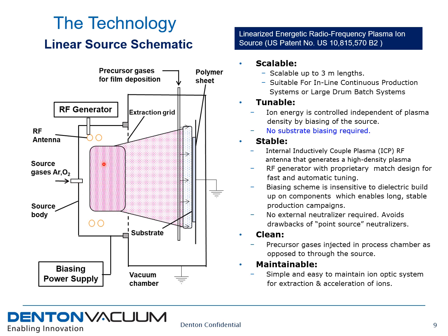and the ions are accelerated to the substrate through a grounded single extraction grid, and by a pulse DC bias that's applied to the source body, and the precursor gases are delivered outside the source and right in front of the substrate. No neutralizer is required as the beam is self-neutralized, and the source is thus clean and can be used for long production campaigns.